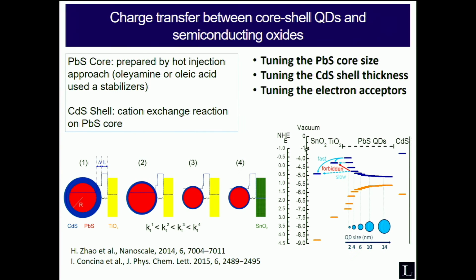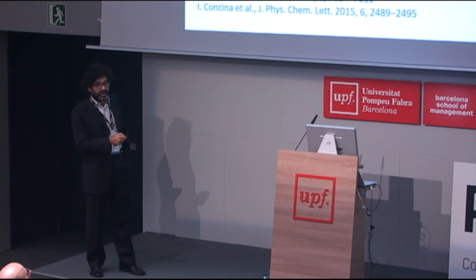Then what we tried for the specific application of solar cells was to investigate the rate of electron injection from the quantum dot to titanium oxide or to tin oxide. We chose titanium and tin oxide because they have a pretty different positioning of conduction band. So you expect that the transfer rate is critically dependent on these two positions. And of course, for such sizes of quantum dots, the injection is absolutely forbidden, while for others it can take place.